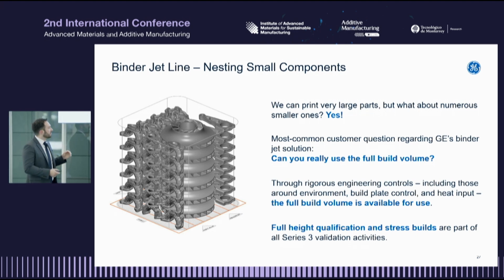So the methods to utilize the full build volume only come from robust and rigorous front-end engineering. We control the temperature of the powder. We control the viscosity of the binder. We have very robust Z-stage control. So can you use the full build volume? Yes. Can I make large parts? Yes. Can I make medium-sized parts that use the full build volume? Absolutely. The beauty of binder jet technology is, in similar style to electron beam, I can nest in Z-space and nothing has to touch the start plate.